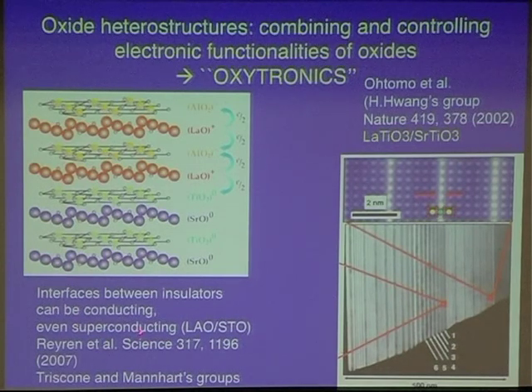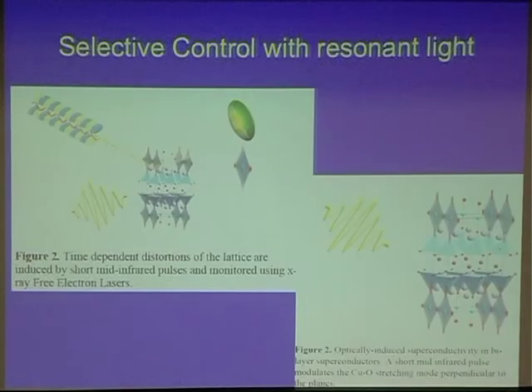This has led, for example, to the discovery of superconductivity in lanthanum aluminum oxide, strontium titanium oxide interfaces, in which you combine two insulators and find an electron gas at the boundary, which is a superconductor. You can do that. You can strain the system in thin films, and so on.